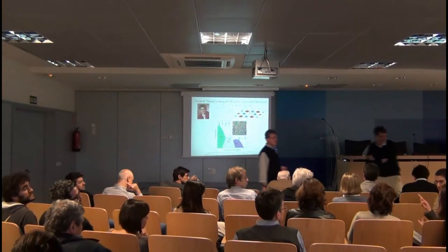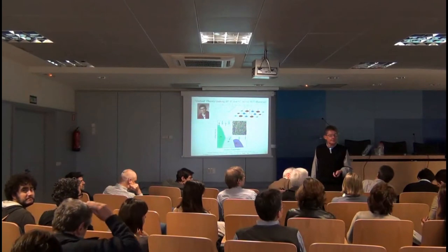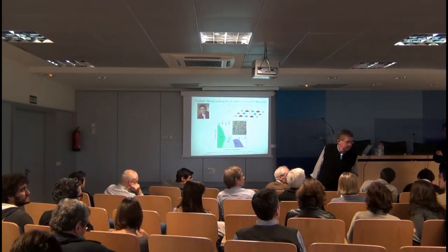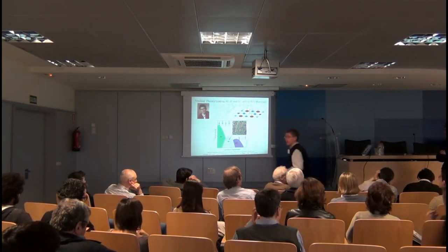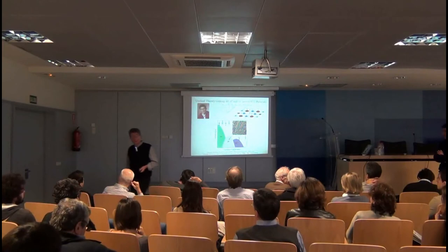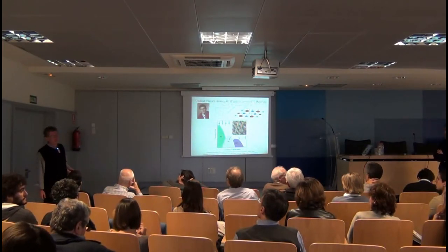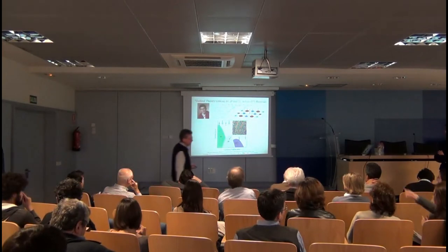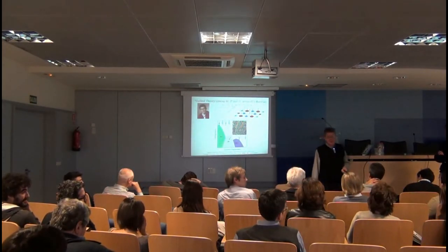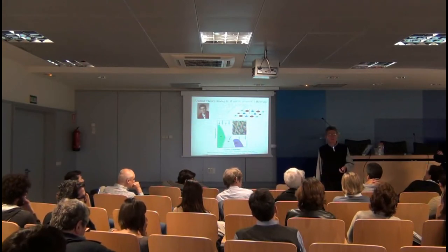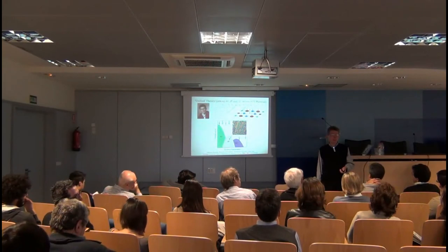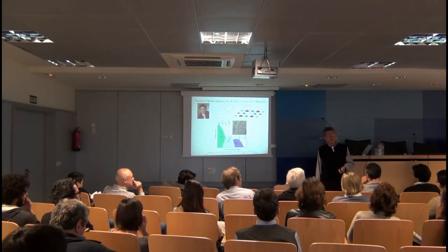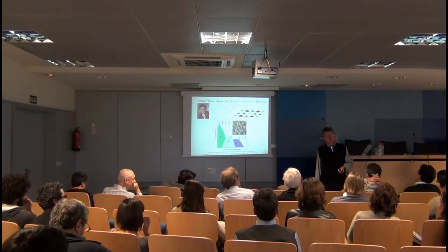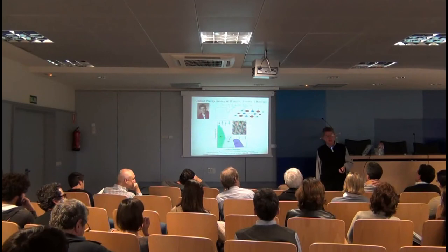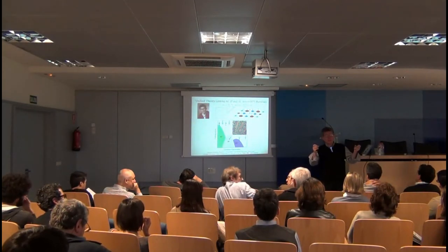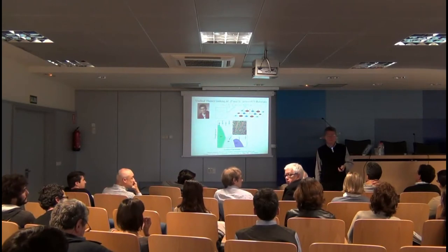Can you say anything with this about the hidden order of uranium ruthenium silicon 2? Say that again, please. If you can say anything about the hidden order of uranium ruthenium silicon 2. Oh my gosh! Wow, that's a different question. Using this technique, you would predict that it's a nematic phase. No, I mean the technique with the measurement, not with the idea. So in our study, we were not able to find any broken symmetry associated with the hidden order in our data sets. Whereas there are a number of colleagues now who are reporting that there's a very tenuous nematic phase there, which only moves the nuclei by a few parts in 10 to the 6. So maybe there's a very subtle nematic phase, but we were not able to observe it.